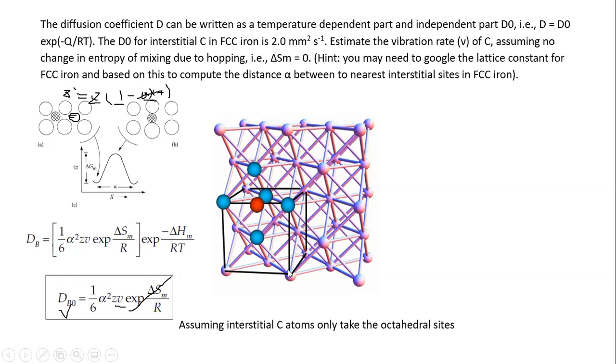Can you follow the lines? You see this is a cube, right? And I didn't highlight all of these things. The nodes here are supposed to be the original atoms, the iron atoms. It highlights a small group of them, and this one is a carbon atom, which is right in the middle of the octahedral cage. So the FCC structure is basically a collection of octahedral and tetrahedral networks, and the interstitial sites for carbon are these octahedral sites. Does this make sense to everyone?